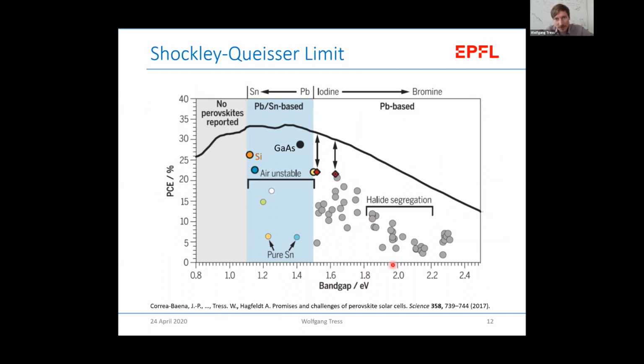And in principle, you get such a curve which is decreasing for lower band gaps because we lose a lot of the solar spectrum due to transmission because we have a wide gap semiconductor, whereas here it is decreasing because we cannot efficiently harvest the energy of the high energy photons in this material. So this means that we in principle lose then in this voltage. And you see here some points for values realized for different technologies.